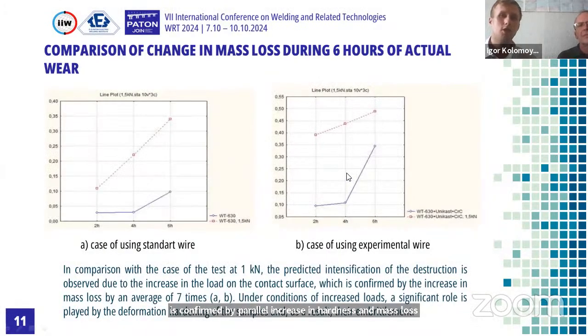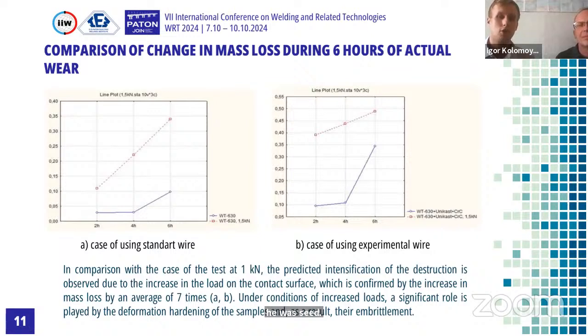Comparison of change in mass loss during 6 hours of actual wear. Here we can see, in comparison with a case of 1 kilonewton, the predicted intensification of the destruction observed due to the increase in the load of the contact surface, which is confirmed by an increase in mass loss by an average of 7 times. Under conditions of increased load, a significant role was played by deformation hardening of the samples, and as a result, their embrittlement.